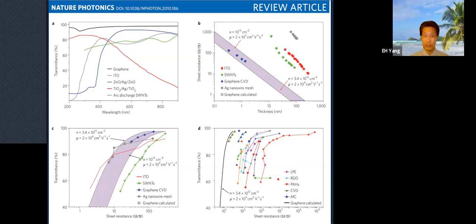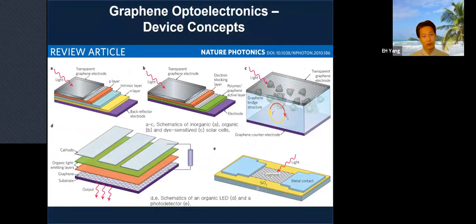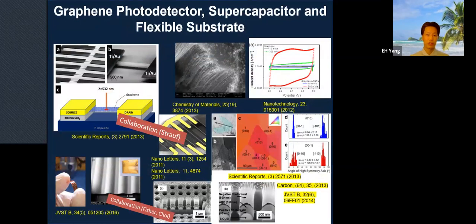On the top right, you see the sheet resistance of different thicknesses of graphene that are compared with those of indium tin oxide in red, right? So graphene can be used as a transparent electrode for various solar cells and LEDs, and can be used as an active material for photodetectors and so on. My own group also worked on growing nano-patterned graphene for photodetectors and supercapacitor and flexible substrate applications. That was 7-8 years ago already. All right.